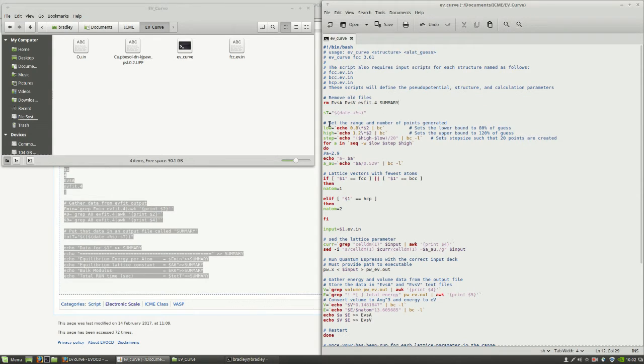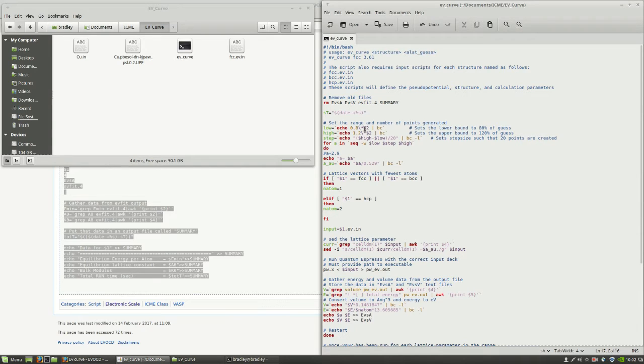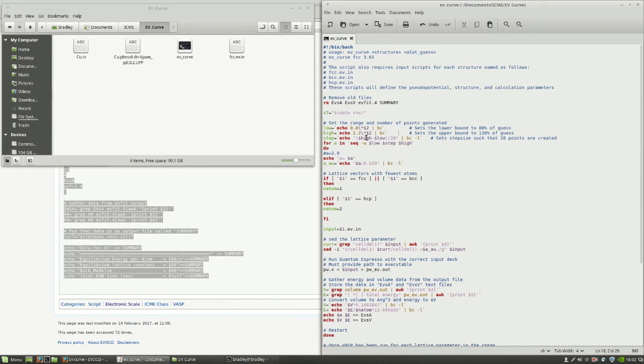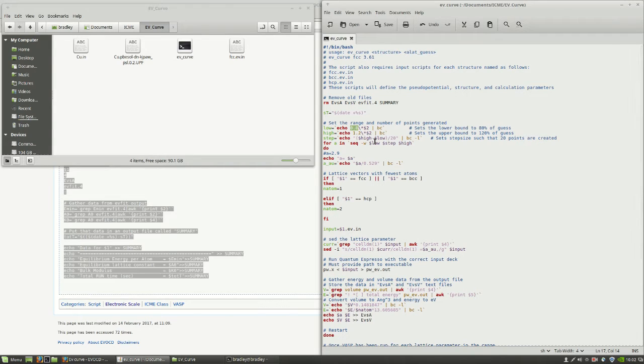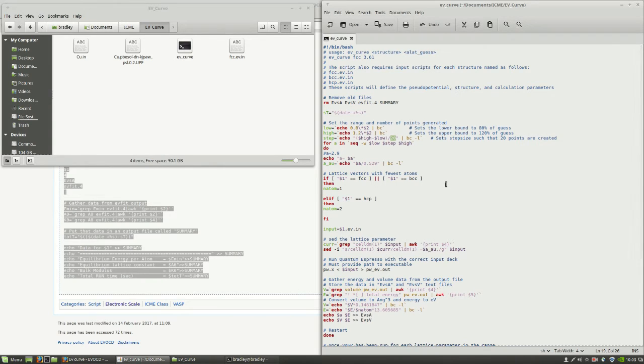Then you can see here, it actually sets up a range of points to check the energy at. It does that by doing an 80% of your guess and 120% of your guess. Your guess is specified when you run the EV curve script. You can edit these ranges if you want to do a wider range or a narrower range. It also sets the number of points. It takes this and sets the step size by dividing it by the number. We're actually going to reduce this because we only want to do a few points for this video.